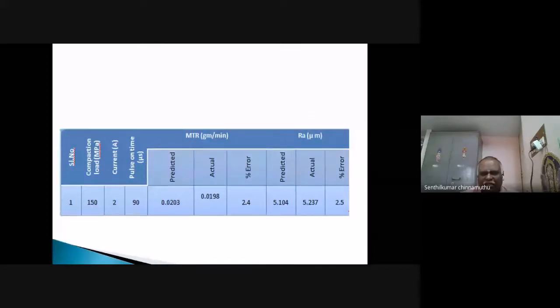which comes under the plus or minus 10%, which is statistically significant, which confirms the good agreement between the experimental and the predicted value, and it shows that it has good reproducibility. The error comes below plus or minus 10, which shows that there is good reproducibility of the experiment.